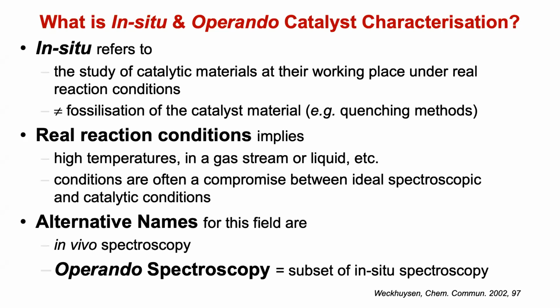So many people are used to the word in situ, Latin, at its place. So that should in principle be at its place, at its working place, but that is not always the case. Secondly, the word in situ is often even used for what I call fossilization of your sample. That means that you have your sample at a high temperature and then you quench it. For example, there are several NMR studies where they use a quenching method. They bring it down to low temperature and then measure it. Especially for magnetic resonance techniques like EPR and NMR, where the temperature really matters due to the Boltzmann distribution for measuring nuclear spins and electron spins, you need low temperature, and therefore they use fossilization methods. Real reaction conditions, what does that mean? High temperature in a gas stream, in a liquid.